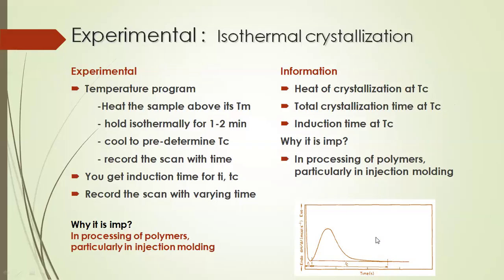Why is this experiment important? For a processor, the injection molding processor defines the residence time of the material in the mold. Because if you know the injection molding process, first the polymer is melted, then it is injected into a mold, and allowed to crystallize in the mold to get the desired shape, and then the material is ejected. So how long the material should stay in the mold can be found out by using this isothermal experiment. So particularly in injection molding, it is very important to find out the crystallization time and crystallization temperature in the isothermal.